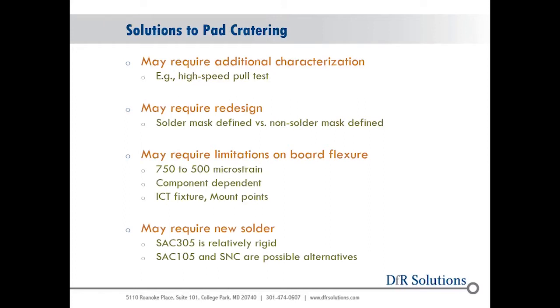Some of the solutions may be using a different type of laminate, so doing some type of testing on the laminates themselves, doing design changes on the pads, making the copper pads larger, and using solder mask defined. There's kind of a trade-off there. If you make the copper pad larger, you're spreading the force out over a larger area and reducing the stress. But by going to solder mask defined, you're actually increasing the stress on the intermetallic. So there's kind of a trade-off.